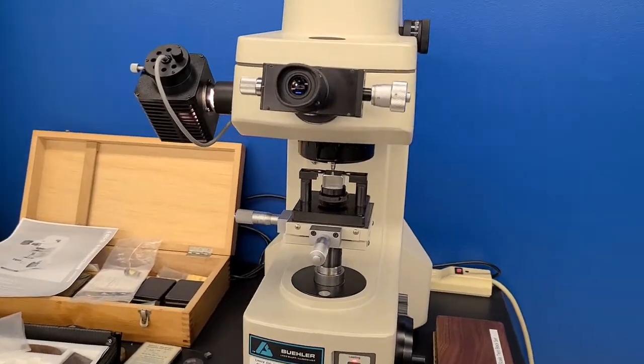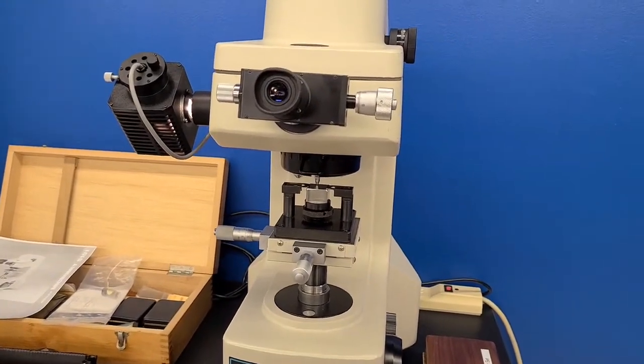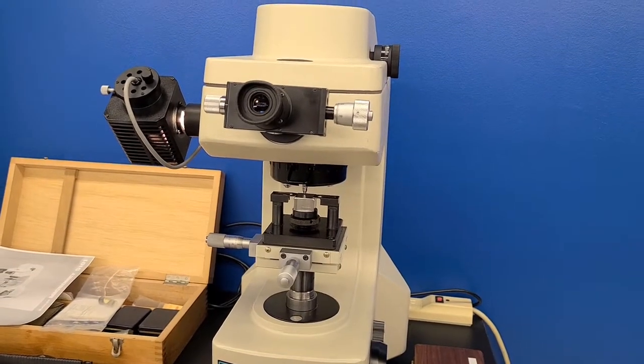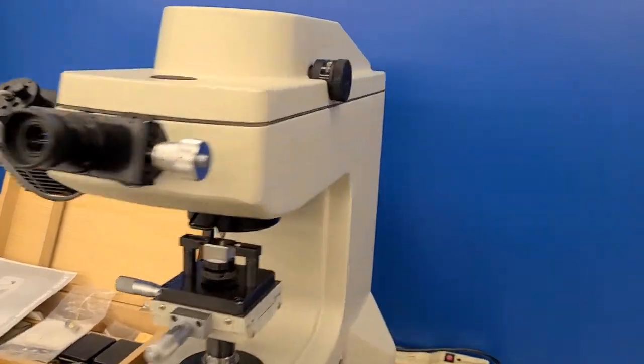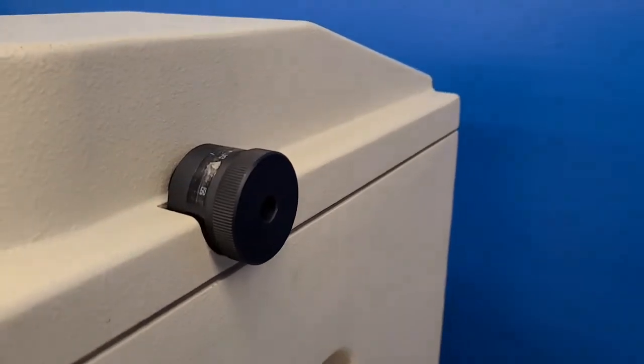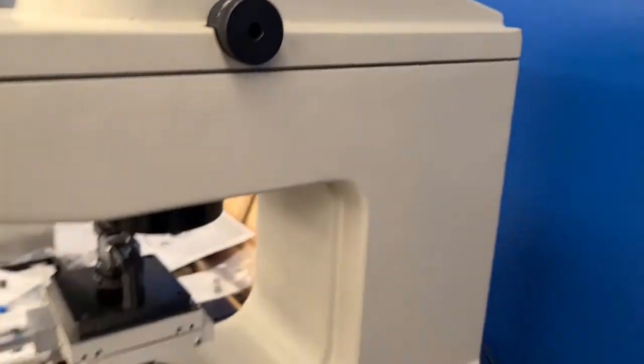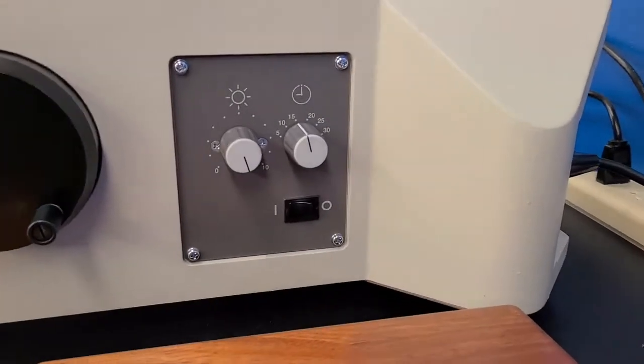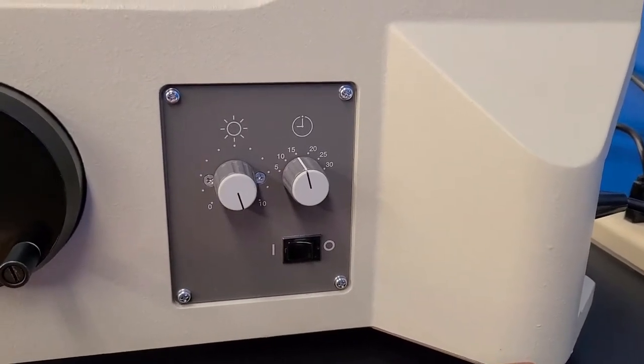So we're over at the hardness tester now. We've loaded up our polished sample. We're indenting it first with 50 grams force, which is set by this module on the top. And we have a dwell time of 15 seconds.